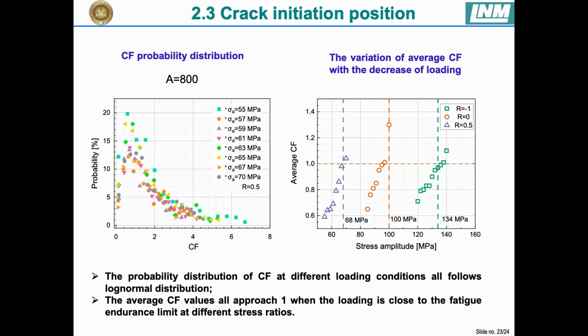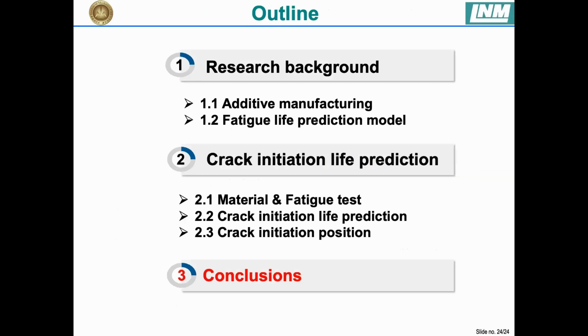It can be seen that the average CF values all approach 1 when the loading is close to the fatigue endurance limit at different stress ratios, which corresponds to the phenomenon of crack initiation position shifting from the surface to the interior. The following are the conclusions.